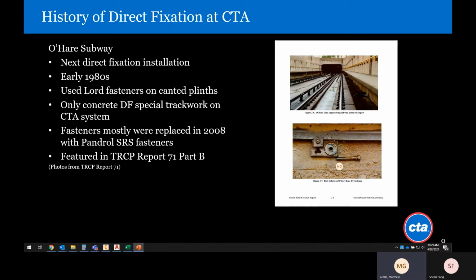The fasteners were mostly replaced with SRS fasteners by Pandrol in 2008, and this area was featured, as you can see on the right, in TCRP Report 71 Part B, which is an experience with direct fixation. And you can see here's an example of one of the fasteners where the anchorage bolt had failed. But the system generally worked out pretty well, and we've been able to maintain it. And then, like I said, basically the tangent fasteners have been replaced with the SRS fasteners. The special track work fasteners are still the originals that we've been able to maintain.